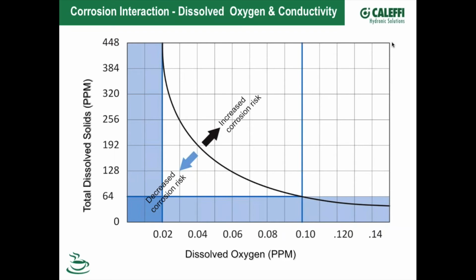But what happens with dissolved oxygen that's not emitted from a system is that the process of oxygen coming in contact with metals in the system creates a natural, call it healthy corrosion on the surface of all the metals. In the case of iron or steel, it would be magnetite or hematite. Magnetite, we'll get into that later, is the preferred method. You get aluminum oxide, you get cupric oxide on copper. So those all become, and those consume the dissolved oxygen.